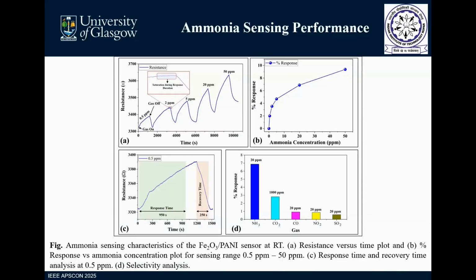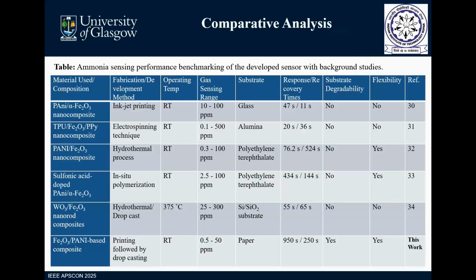We compared our study with other works on PANI and Fe2O3, and we have seen that our sensor is both flexible as well as degradable compared to the others. Most of the sensors work at room temperature, and only the WO3 and Fe2O3 nanorod sensor shows its sensitivity at 375 degrees Celsius. Otherwise, most of them show good response, but they are not biocompatible and biodegradable.